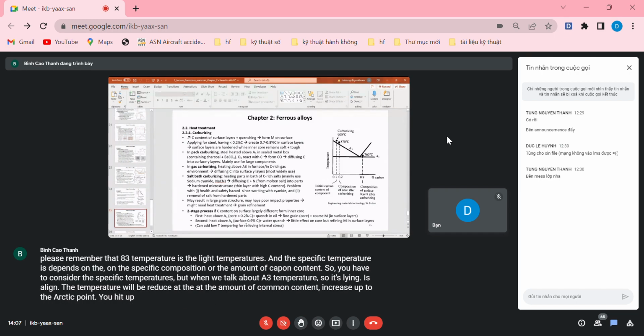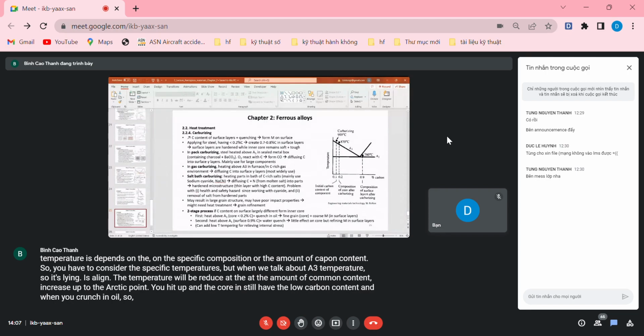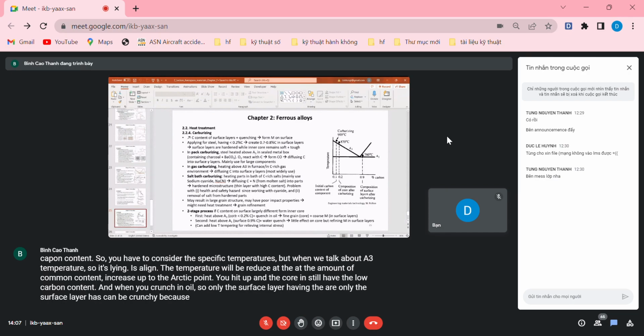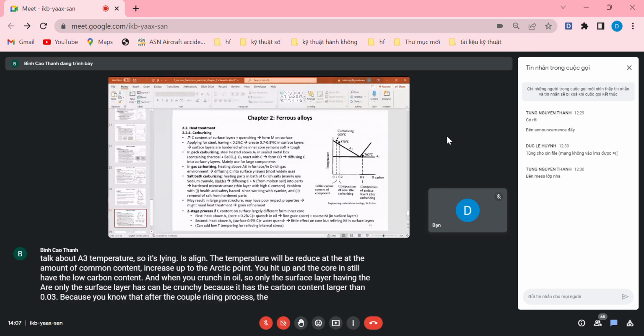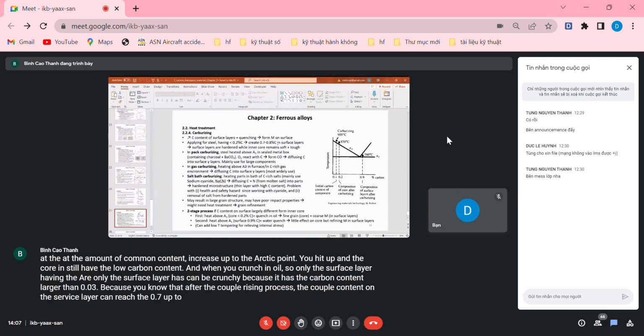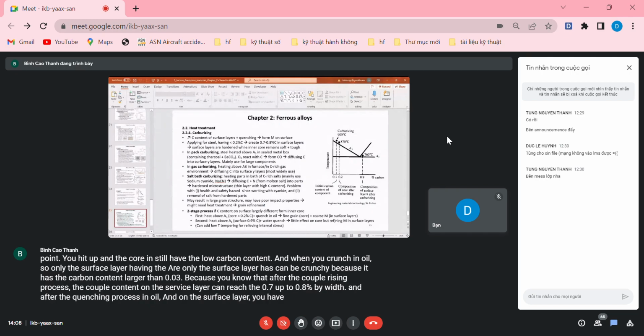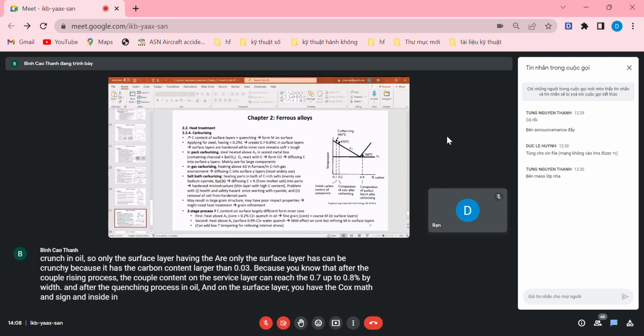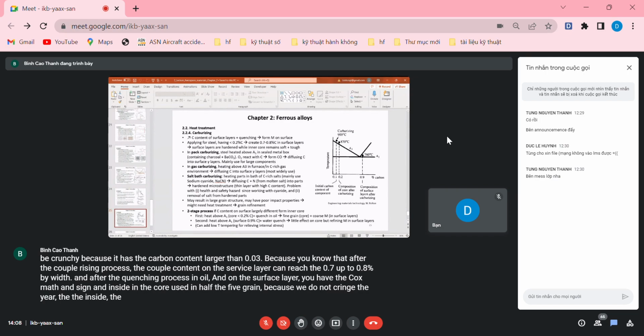You heat up, and the core will still have the low carbon content. When you quench in oil, only the surface layer can be quenched because it has a carbon content larger than 0.3%. After the carburizing process, the carbon content on the surface layer can reach 0.7 up to 0.8% by weight. After quenching in oil, on the surface layer you have coarse martensite, and inside in the core you still have fine grain because we do not quench the core.